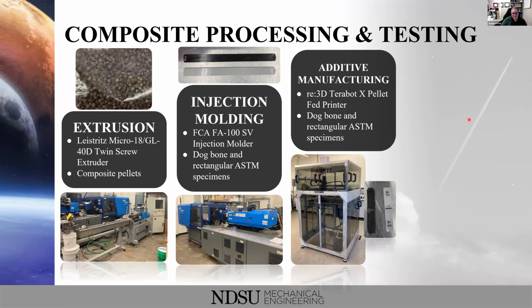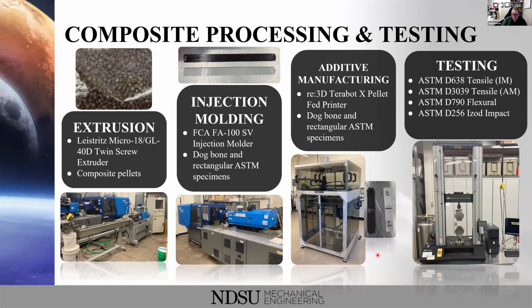And then we also did some additive manufacturing. As Samantha said, we have a Re3D Terabot X pellet fed printer. If I'm not mistaken, I believe it's also the very first commercially made Terabot X, which we've had here for a couple of years. We basically 3D print the exact same specimens that we injection mold. There are some slight differences to our tensile bars, the dog bones, because there ends up being some stress concentration points when we additively manufacture the exact same shape that comes from injection molding, but they're relatively similar. And in terms of standards, they do meet the same standards.